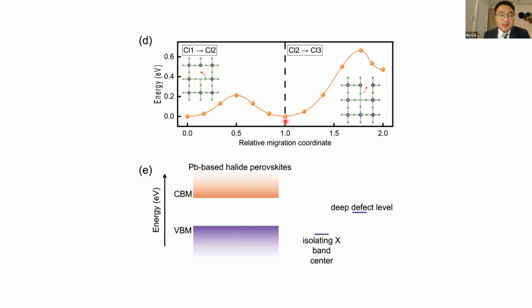Furthermore, we found the energy of the band center of chlorine is lower than the VBM of most halide perovskites. That means we can suppress the ion migrations by decreasing the mismatch of band centers without introducing deep defect levels. So it is theoretically feasible to enhance the stability without losing their efficiency.